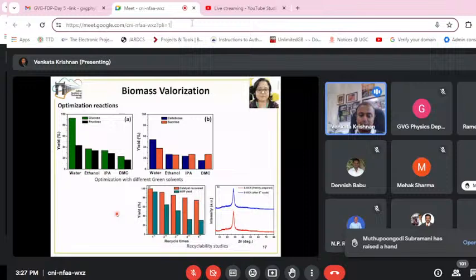So we did the recyclability of the catalyst, and we found that although we are able to recover the catalyst to quite a good extent, the HMF yield still decreases over a period of time.